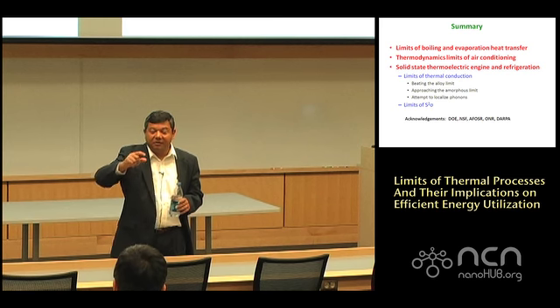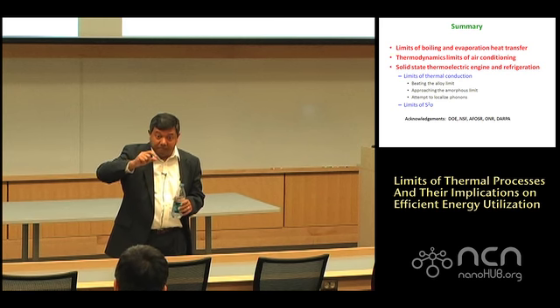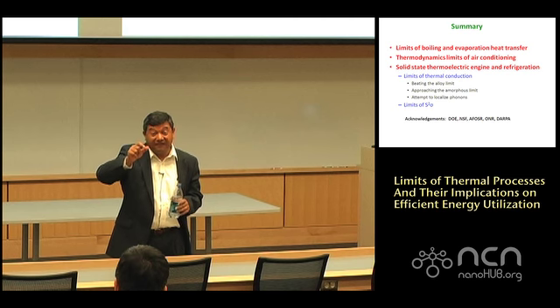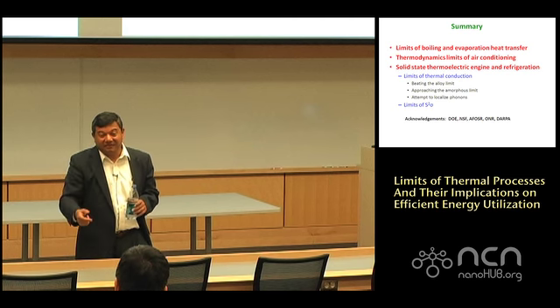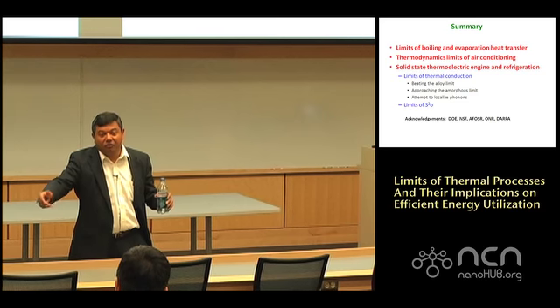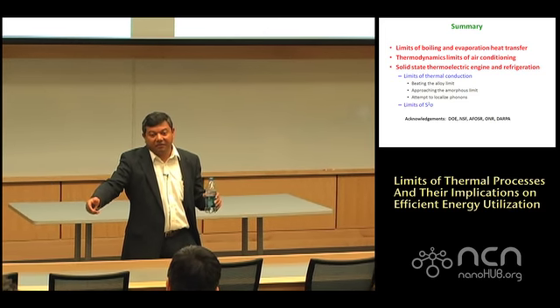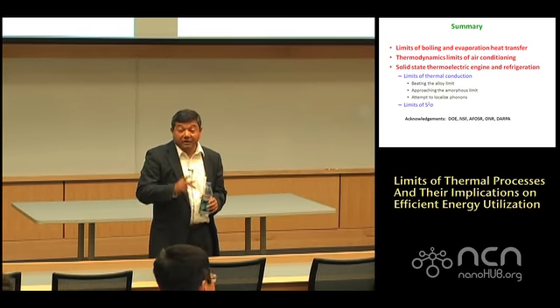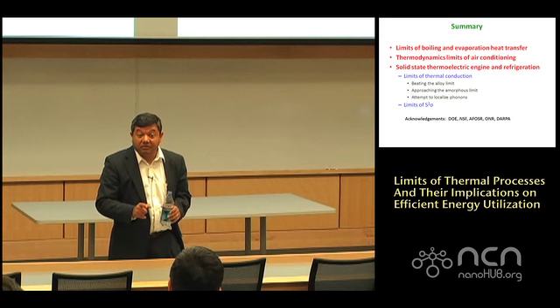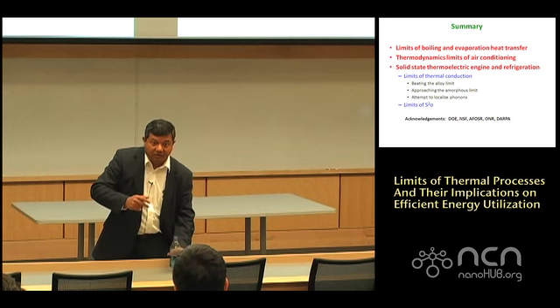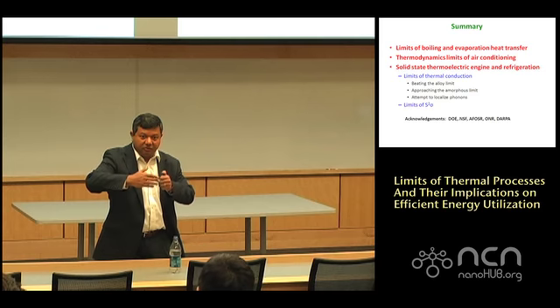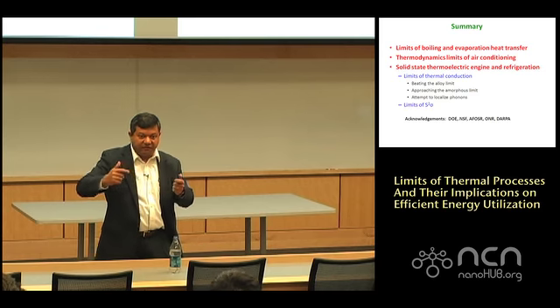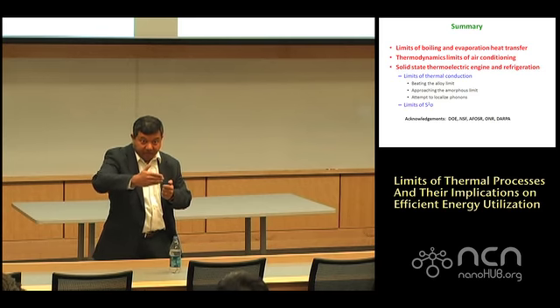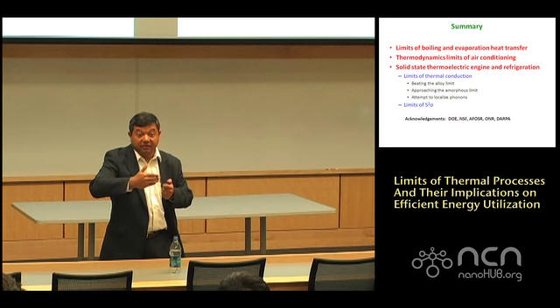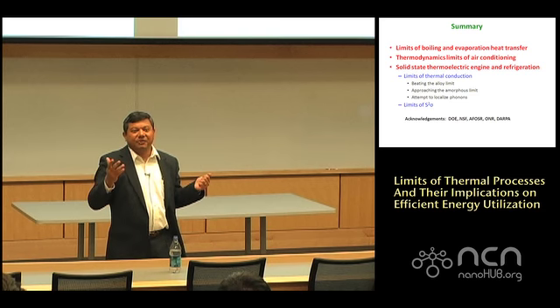But if you make it random, you get essentially resonant coupling between the K vector of the phonons and the K vector of the roughness. And then you can do it. So randomness over a whole range of length scales is a good thing out here. But you cannot localize the fundamental modes. The fundamental acoustic modes, the torsional mode, the two transverse modes, and the longitudinal mode cannot be localized by roughness. So for that, it's a wave scattering problem.